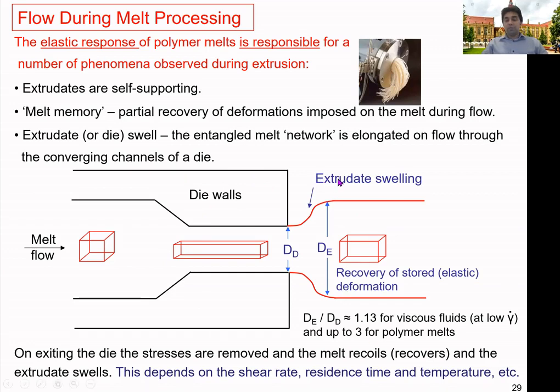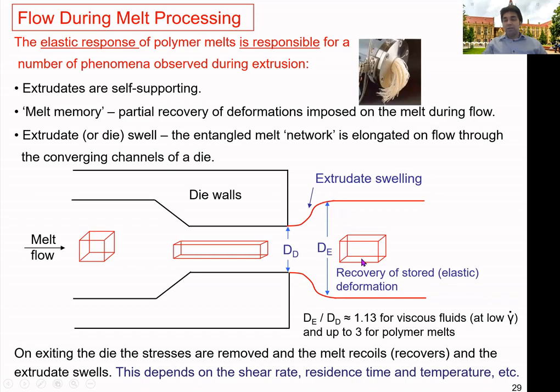Die swell is something we need to control during manufacturing processes. For example, in pipe extrusion we don't want unwanted expansion — we need to maintain a certain wall thickness, outside diameter, and inside diameter. Therefore we have to consider die swell when designing the die and when selecting the process conditions. These are some of the important factors related to the elastic response of polymeric material in the molten state.